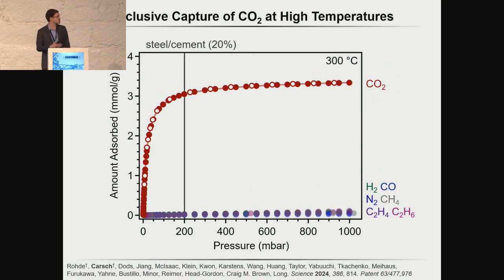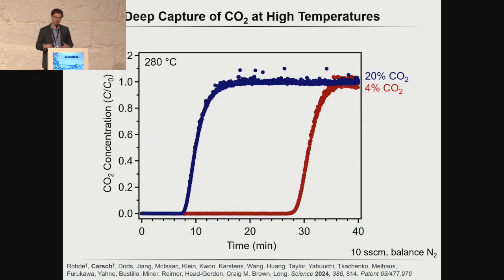This is the first adsorbent that can actually operate with high capacities at these elevated temperatures, where we have fantastic affinity for CO2 based on chemisorption, and we have no affinity for other gases that may be present in the stream. We can then undergo breakthrough measurements at these elevated temperatures. We can see that as we go from 20% CO2 to 4% CO2, we increase the breakthrough time. Or another way of putting it, it takes longer for our adsorbent to saturate. Where we have deep capture, as we're capturing all the molecules of CO2 until our adsorbent starts to reach saturation.